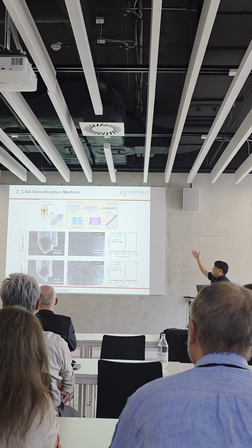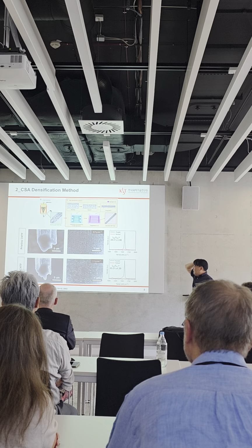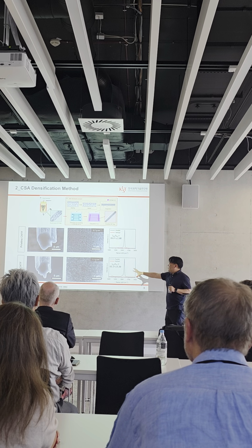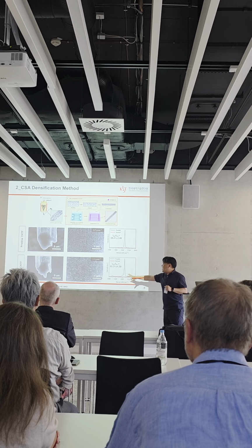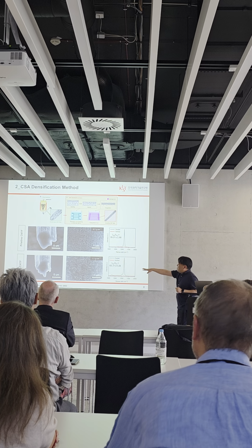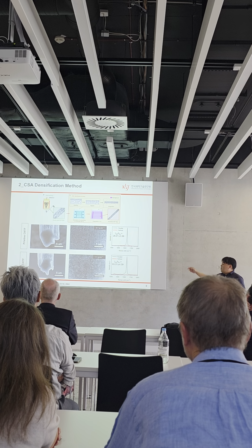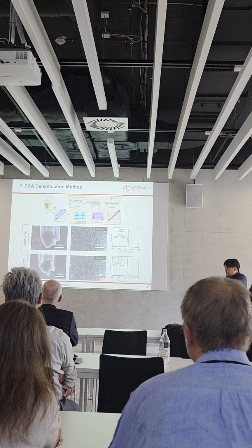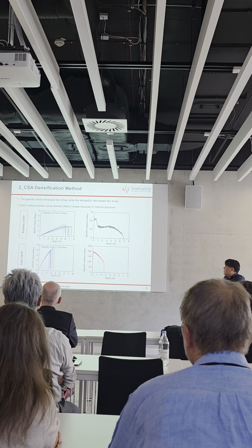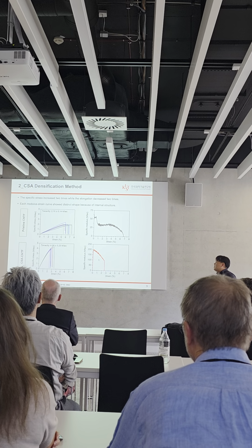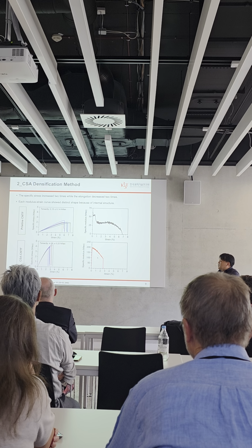We performed this process and really saw a difference. It becomes denser, with 10% stretch from the original fiber, and its alignment is increased a lot.